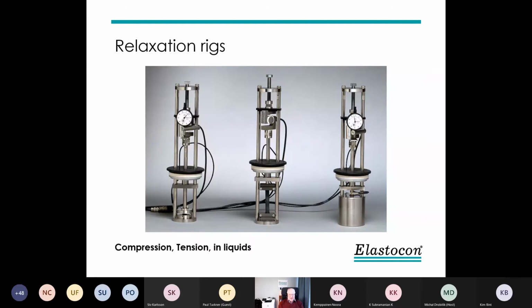It's possible to test in several ways. Compression is the normal one, you see the first. If you test in tension, we use a strip and clamps. And then to test in liquids, we have containers. There are 2 versions of containers. You can use ones that are not airtight. That means that they are not really airtight, and then you cannot test too volatile liquids or at too high temperatures. And later on, we developed airtight ones up to 3 bar pressure. And then it's possible to measure oils and fuels and liquids, and also water up to 145 Celsius. That means 3 bar is the maximum pressure limit we have.